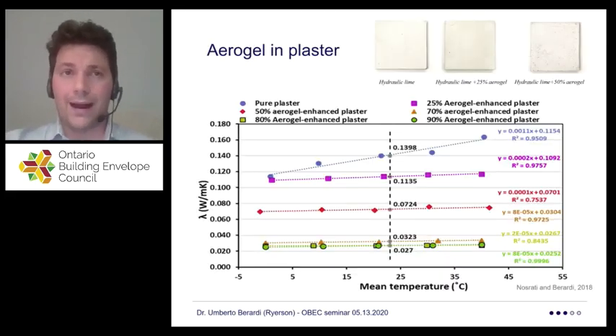We did the test for aerogel plaster, blankets, same story. The reality is, the more dense a material is, the less important is the temperature. So when you start adding materials that are packed together, then temperature is not any more important because porosity is not any more important. So just to give you the sense, all these kind of plaster in the yellow, green, orange line, they were full of aerogel. The aerogel was filling the cavity, and then the thermal conductivity was almost independent from the temperature.